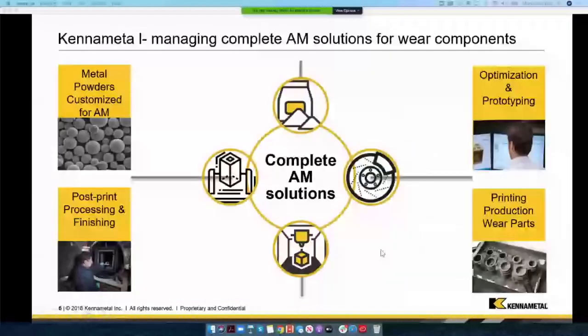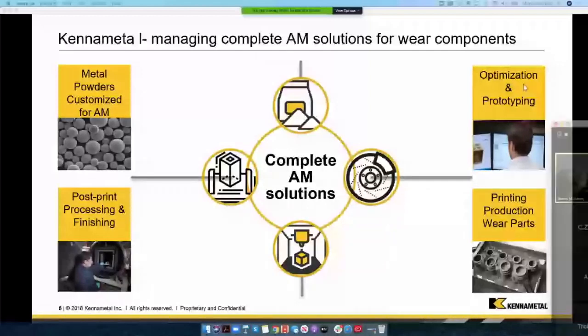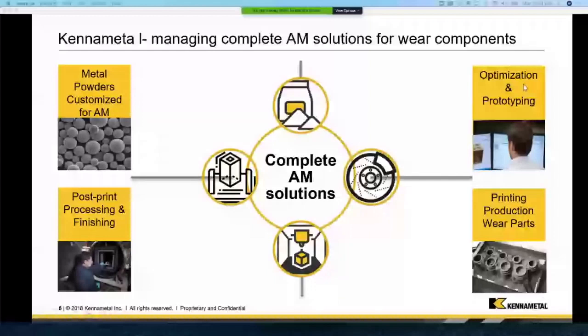So when we look at completing the solutions for wear components, it's not unlike what you have in a lot of other segments, whether metal or plastics or otherwise. But in this case, we're managing the metal powder characterization and customizing that for additive to make it both more printable and to get the desired properties in the end. We are doing prototyping and optimization of the design for manufacturing. And then we are printing production components for the wear markets and also focusing on post-print processing and finishing that would include, in this case, sintering or hipping, as well as finish machine grinding.